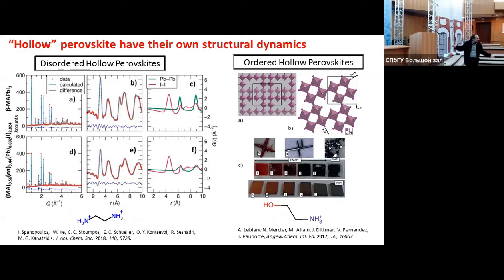basically we did again total scattering, and we're trying to see the correlation between lead-lead and iodide-iodide interactions. We see that iodide-iodide interactions don't change from the pristine material compared to the material loaded with ethylene diamine. But what changes significantly is the correlation between the lead atoms. That, to my eye, suggests that ethylene diamine actually replaces the metal rather than the cation. And this is how we end up with a scenario that we drill holes in the perovskite. And because we cannot see these holes in this system, we call this type of materials hollow perovskite or disordered hollow perovskite.